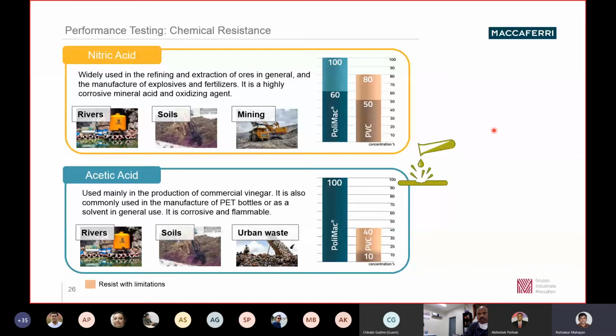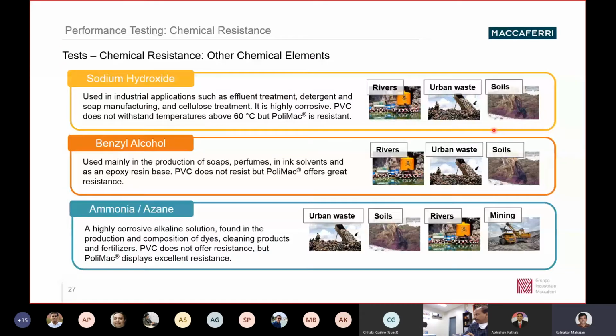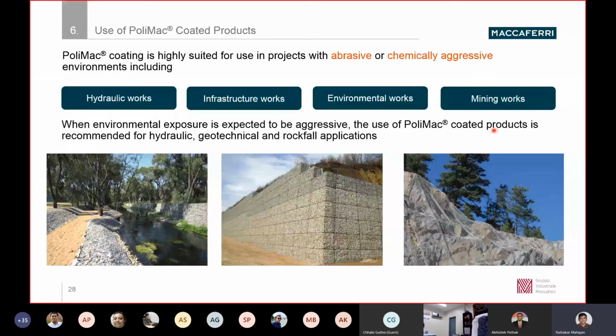Then the test results, what we have seen is that in many instances PVC cannot resist the chemical aggression, but Polymac resists perfectly, something like ammonia or benzyl alcohol or many other chemicals. So Polymac resists it, I would say, perfectly. So when chemical aggression is an issue, the presence of a resistant coating is essential to protect the basic steel wire from rapid corrosion so that the durability can be ensured. So these products are recommended for use in hydraulic, mining, infrastructural works and environmental works, and they are more suited for abrasive or chemically aggressive environments, or, I would say, low temperature, or where the UV radiations are higher. There you can use them.